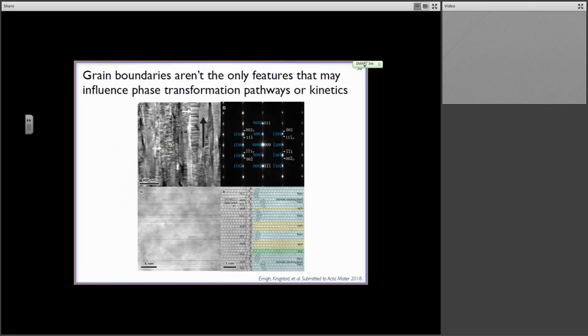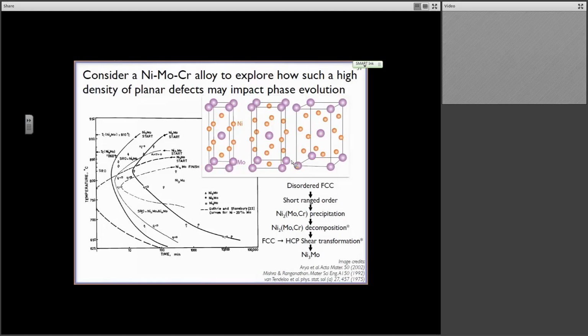Because of the high density of these planar defects, it's actually about 50% HCP, or hexagonal close packing. You can see that from the high-resolution image down here. Rather than just having a single plane that's affected by a twin or stacking fault, we actually have large regions that are impacted by this, and that's manifested in its diffraction pattern as well. And so I want to come back to this because there's more complexity here than I'm giving it justice, but I don't necessarily have time to get into it. But basically what I want to show to you is that by using these planar defects, we can look at these sorts of sluggish phase transformations that are quite interesting.